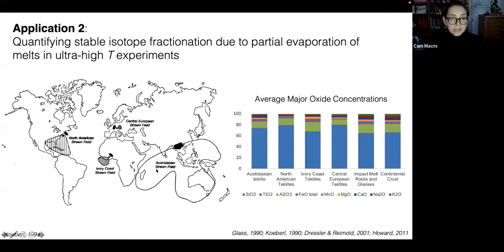And that brings me to the second study that I'm going to tell you about. This is the study where we're looking at stable isotope fractionation due to partial vaporization of melts. This is that map that I showed you earlier of the different tektite strewn fields. On the right, I'm showing you a stacked bar chart that shows the relative average major oxide abundances for tektites from each strewn field. These show that tektites have roughly similar compositions in general, with some inter-strewn field variations. But if we consider the average composition of all impact melt rocks and glasses combined and compare it to continental crust, we find that their compositions look very similar.